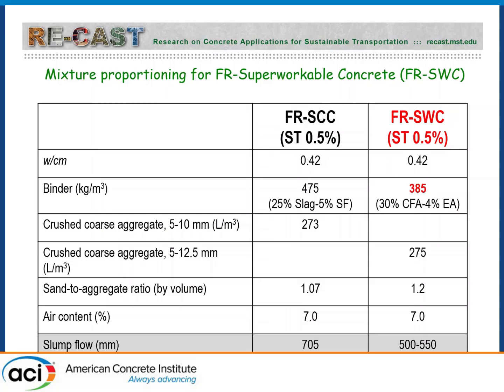You can see in terms of water to binder ratios, they're both the same. So we want high performance. They're designed for durability and service life. And that's secured by reducing the water binder ratio, but also using a binder that will give you very good performance. So in this case, you see 25% slag cement and 5% silica fume versus 30% fly ash. In the Midwest, we have a lot of C fly ash and no silica fume. If you look at the 385 that I put in red, this is to underline that with a super workable concrete, your concrete does not need to be as fluid, so you can save quite a bit on the binder, you can save quite a bit on the paste.